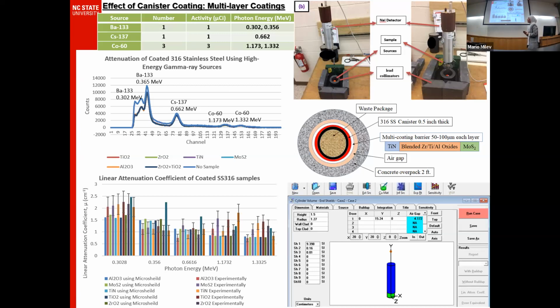From all the different coatings we used, like aluminum oxide, molybdenum disulfide, titanium nitride, titanium oxide, zirconium oxide, we observed that the sample with double coatings offers better attenuation than the one with a single coating or no coating at all. This is very good to enhance the shielding properties because you have a very high density material but a very small thickness, which helps increase the attenuation properties.